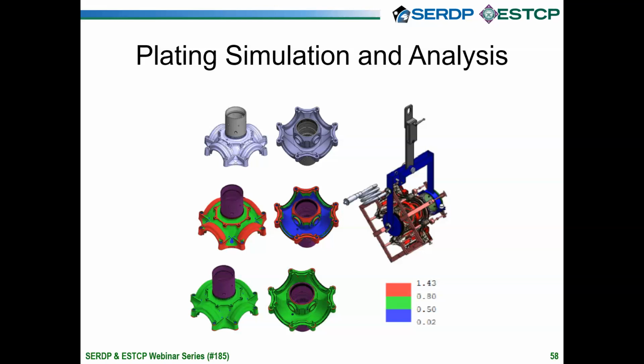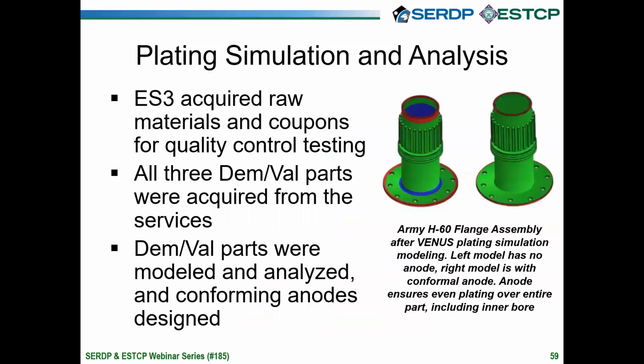So after running the initial Venus analysis, which would be your second line here, that means no conforming anodes have been put in place. It's just plating with the tank anodes that are on the sides of the tank. You can see the different thicknesses that you're going to get in the blue, green, and red areas. So the requirement for the specification is to be between that 0.5 to 0.8, which is the class 1 thickness requirement. After you place conforming anodes, theoretical conforming anodes in space, and then rerun the evaluation, you can see that all of that blue area goes away, and then everything is held together using fixtures. So we use 304 stainless steel primarily to hold nickel 200, which would be the dark red components that you see there, to make sure it plates in all of those areas that would be highly underplated, if plated at all, in the blue shading there. Going to the next slide, 59, Greg.